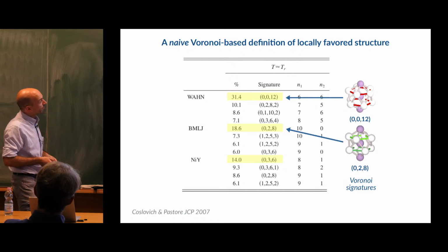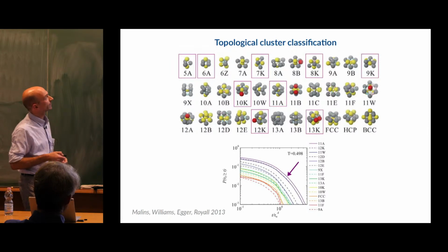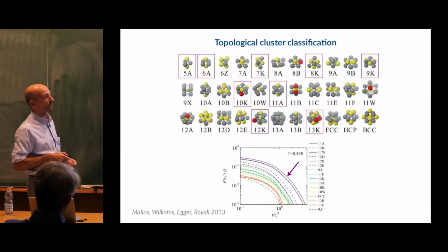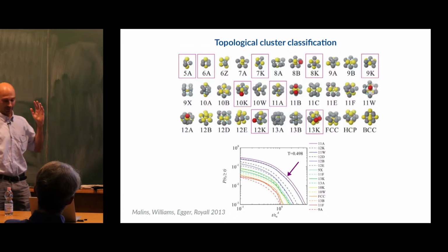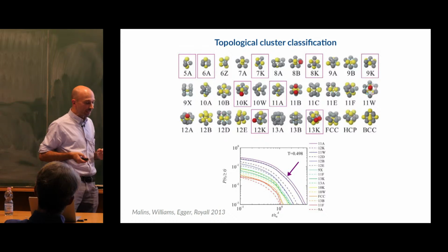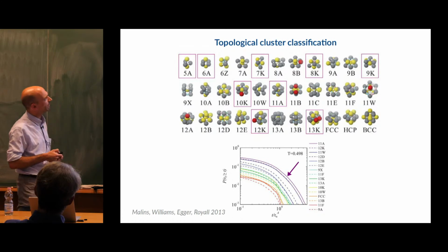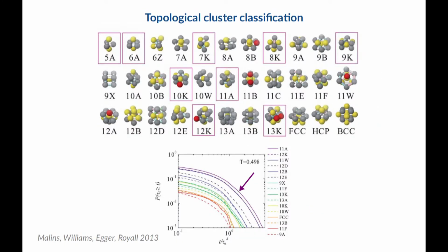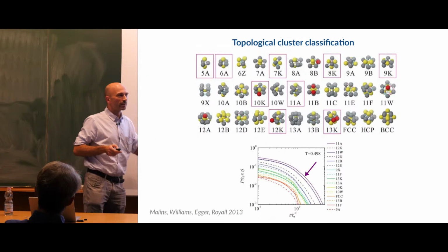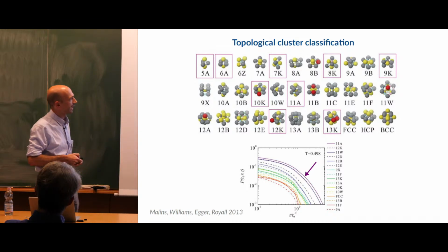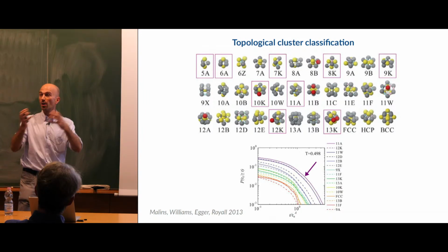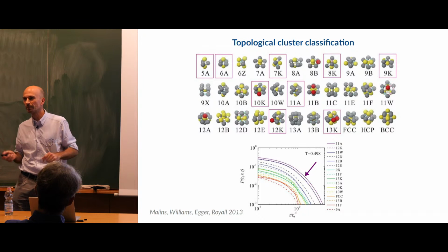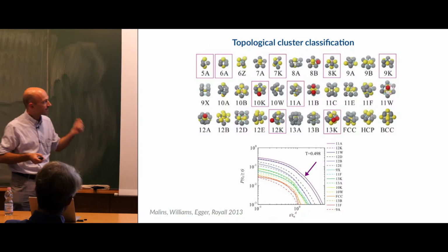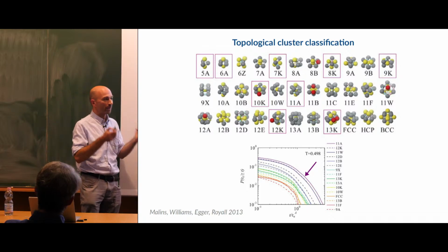So Paddy Royall has his own way of looking at locally favored structures. We heard about it quickly in the talk by Laura, the topological cluster classification. And what Paddy does is look up an extensive database of possible minimal energy clusters of the system he has, and then make statistics of all these possible arrangements. But because of the way these clusters are made, they can overlap with one another. They can be contained within one another. And so it's not easy to count them. So what Paddy does, he also looks a little bit at the dynamics of these objects. And in particular, he looks at the lifetime. And then he says, okay, well, the structure that has the longest lifetime is going to be my locally favored structure.